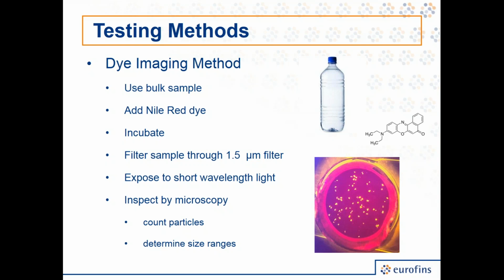And then we expose what is captured on the filter to short wavelength light, somewhere in a range of 500, 510 nanometers. And if you look at the fluorescence that appears at 530 nanometers or greater wavelength, you'll see little glowing dots on the filter. And so those are relatively easy to see compared to undyed plastics. And so it makes it possible to go in and actually count them and characterize these things. So we go through a step where we're going to do some microscopy to come up with particle counts and also determine sizes. So two key pieces of information.